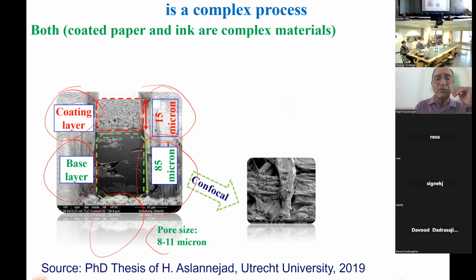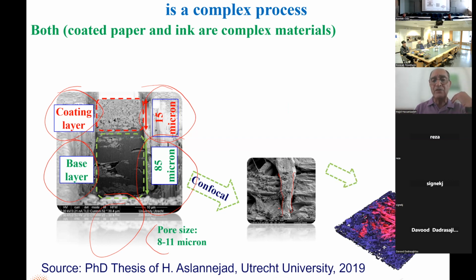Here you see images from confocal laser that we have prepared ourselves. You can see the fibers very nicely, very clearly, their surfaces. And we can also see penetration of ink that has some fluorescent material in it into that paper. The coating layer, however, has very tiny pore sizes, 100 to 600 nanometer. And so we cannot use confocal laser microscopy.